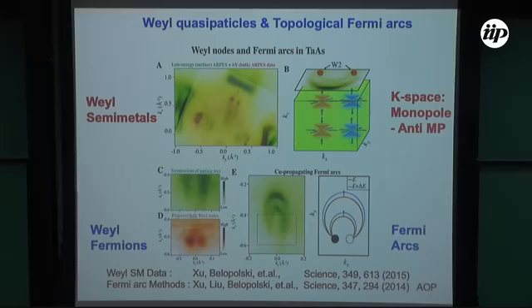And we know those are Weyl nodes because they have a spin texture. They're non-degenerate. Dirac would be degenerate, right? Dirac would be 4-fold, and the Weyl node is 2-fold. Okay. So then we repeat that all over the momentum space and figure out how many Fermi arcs there are, how many Weyl nodes there are. And this is our experiment.